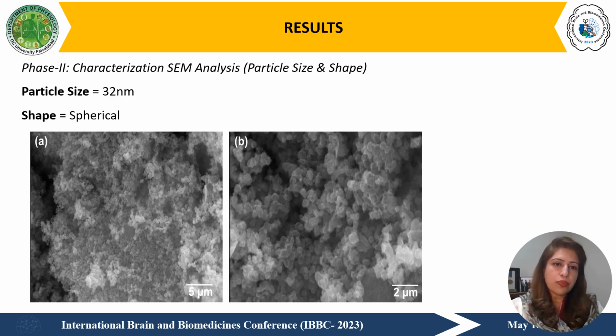Scanning electron microscopic analysis was carried out to calculate the particle size and its shape. Scanning electron microscope analysis of titanium oxide nanoparticles synthesized by the jasmine flower extract revealed prominently spherical shaped clusters with good dispersion at 5000 magnification. These titanium oxide nanoparticles synthesized by the jasmine flower extract were about 32 nanometer in size.